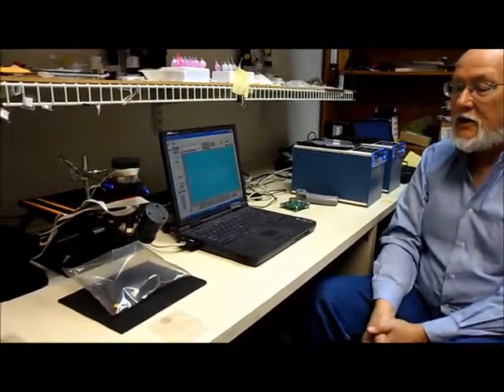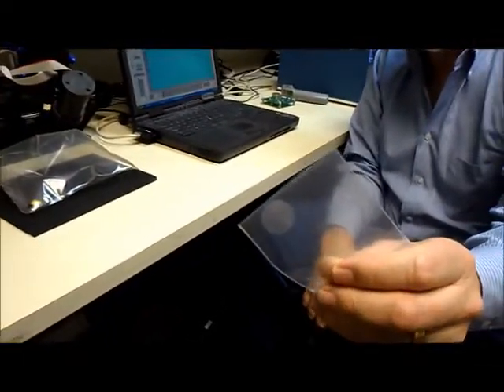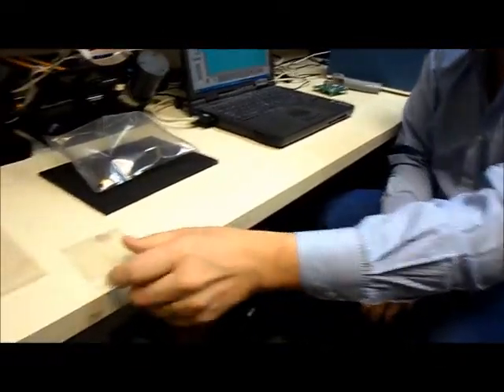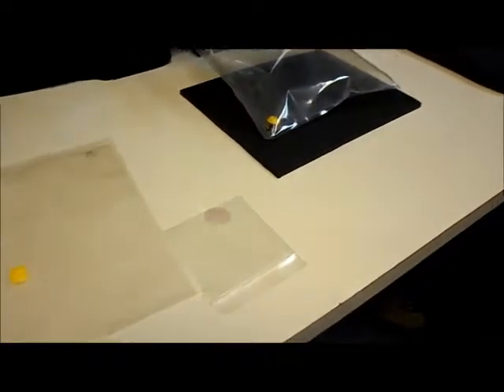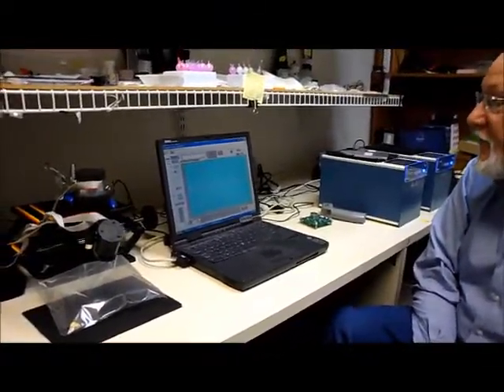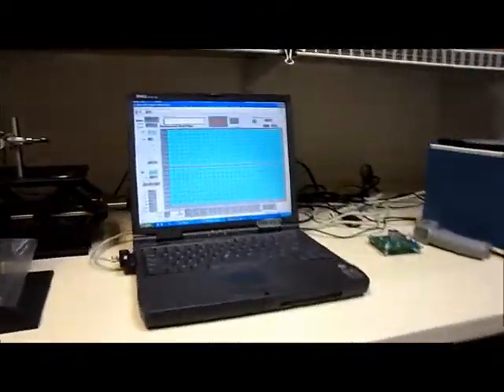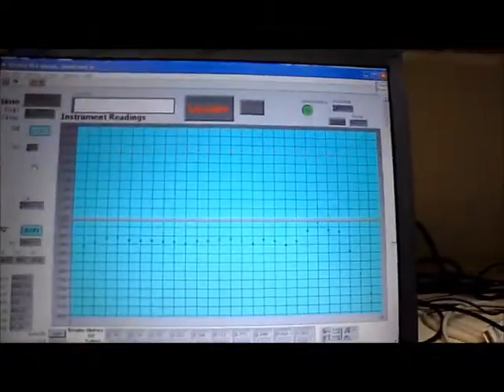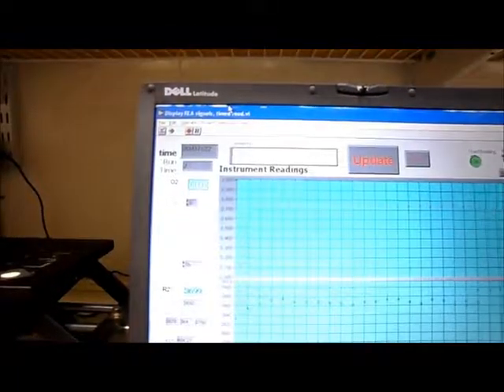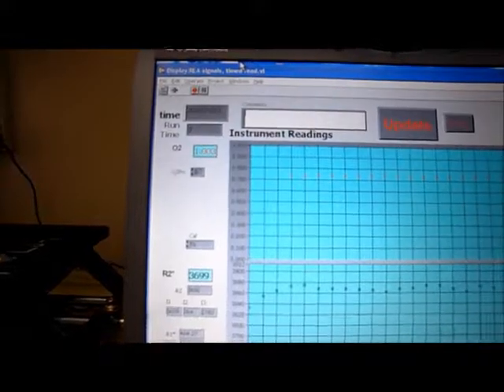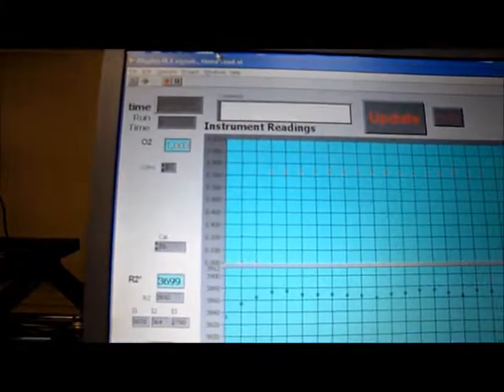I've got another film material here, one that I showed you earlier, which is a little more easily seen perhaps with the red color in it. And I had demonstrated that under the ultraviolet light. We're already seeing, since I removed the tape, the effect of oxygen going into the package. I'll allow the camera here to take a view so that you can see the oxygen signal. Oh, there we go. Hello, Windows. The signature is going up here.